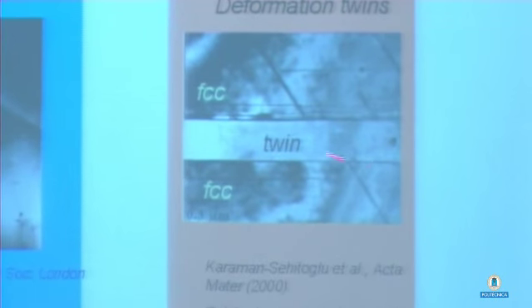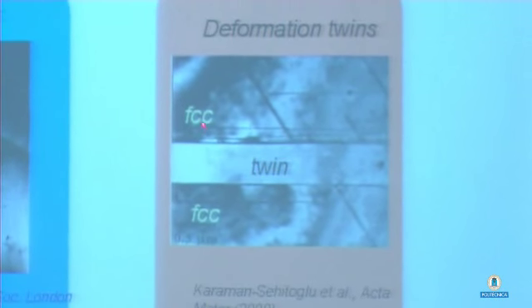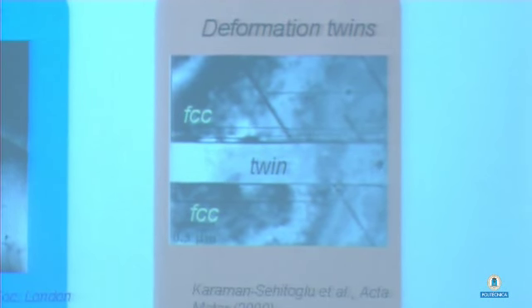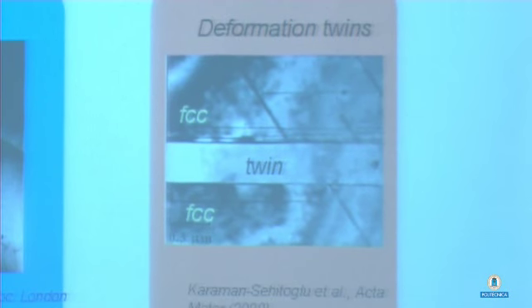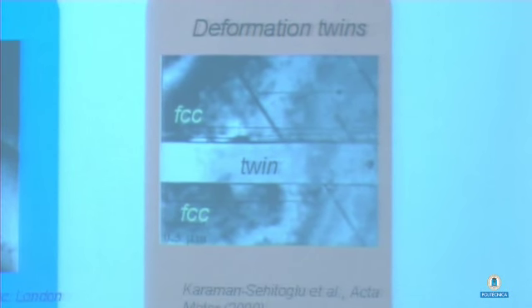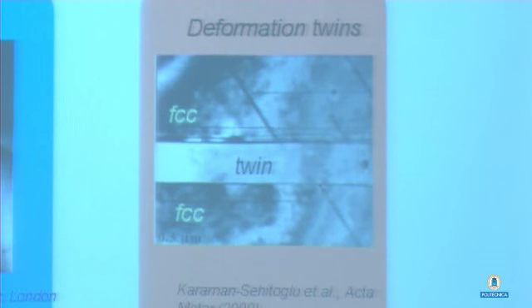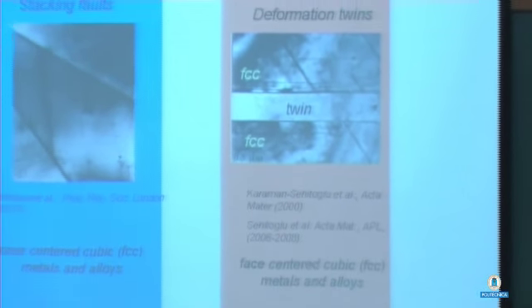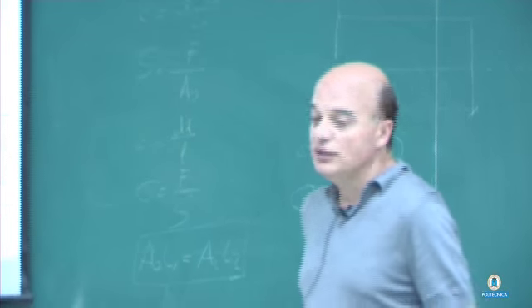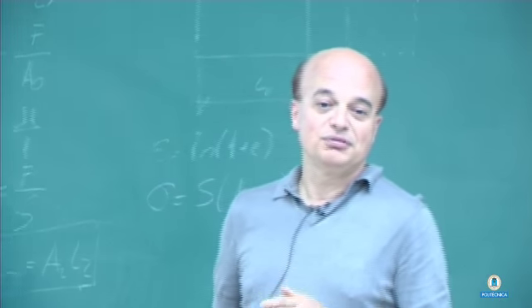And this is the twin, and this is FCC material in this case, and these are slip bands. For example, the slip bands are impinging on the twin, and that affects the deformation behavior, the stress-strain behavior. These things have been published over the last 10 years. First, I'd like to describe to you the philosophy of the research.